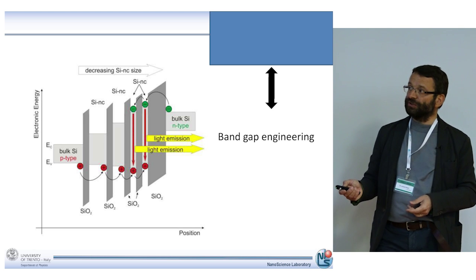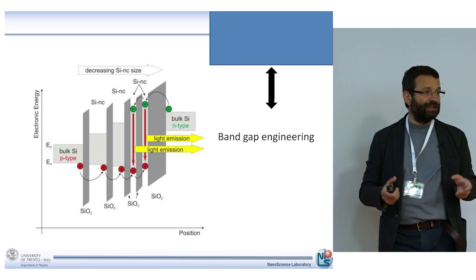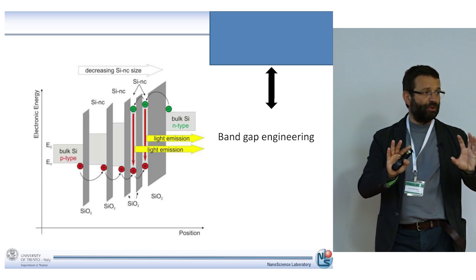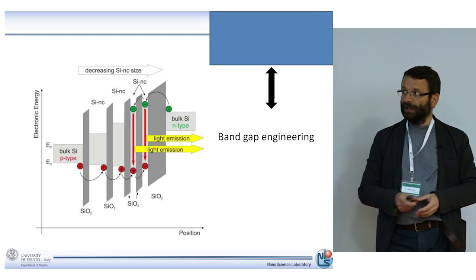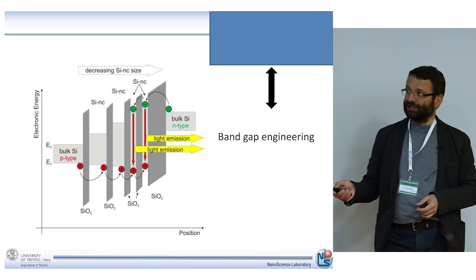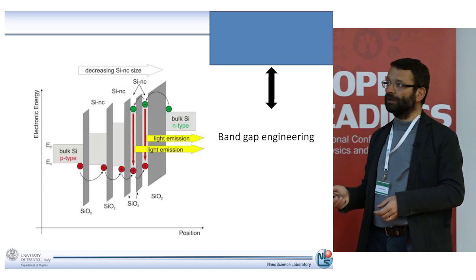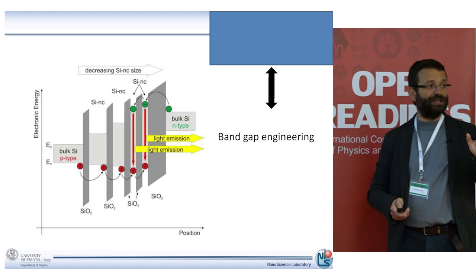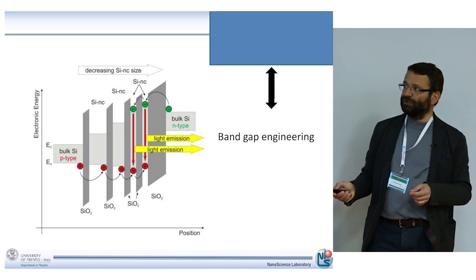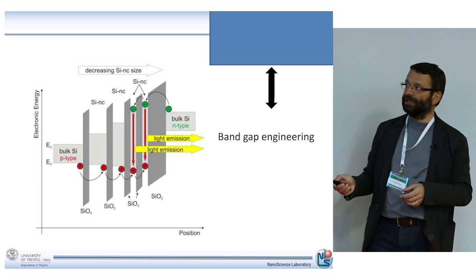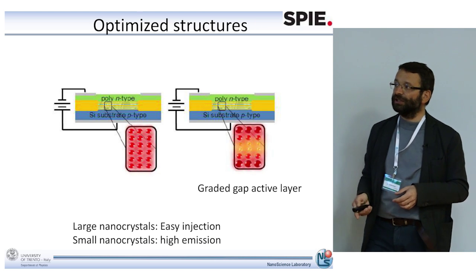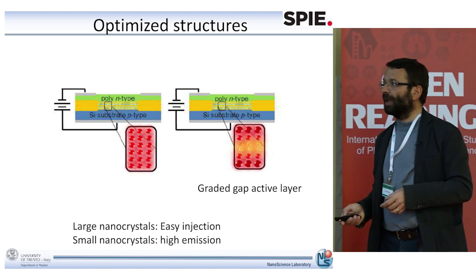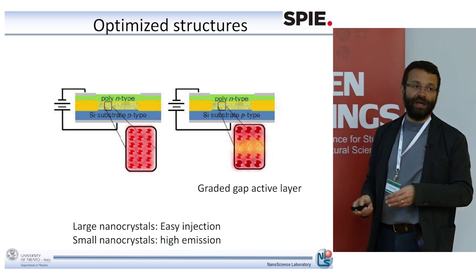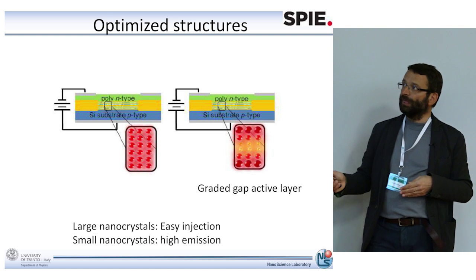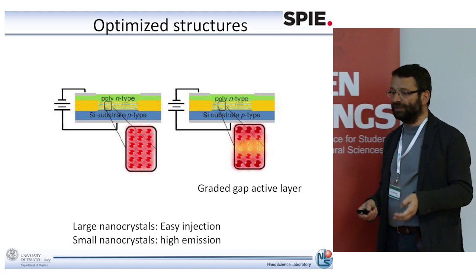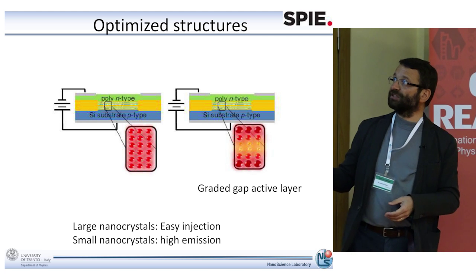And the idea is the following. Since it's easy to inject into large nanocrystal, we put the large nanocrystal towards the contact. But then we get a much larger quantum efficiency in the small nanocrystal. So in the central region, we put the small nanocrystal. So we produce a graded gap active layer, large nanocrystal to the contacts, and small nanocrystal in the center of the layer. And here is the result. This is the luminescence when we have a periodic sequence of multilayer. And this is the luminescence that we get when we have this graded energy gap system, much stronger than here.